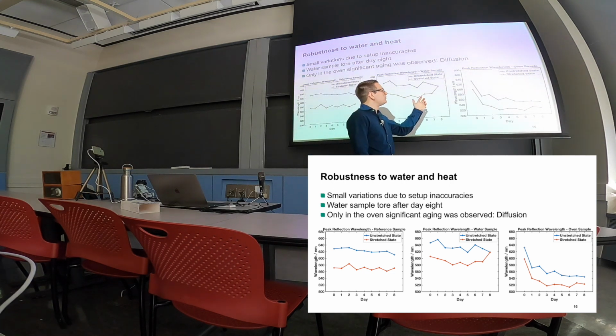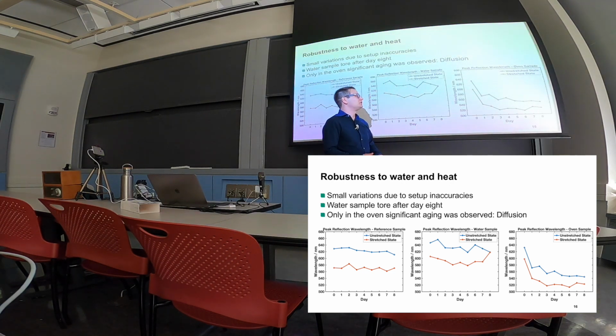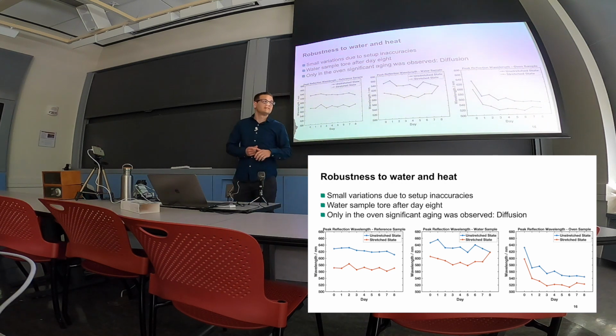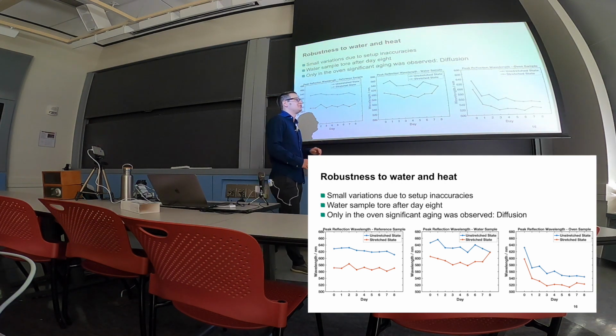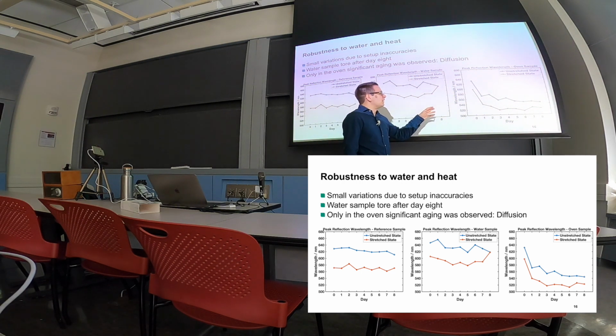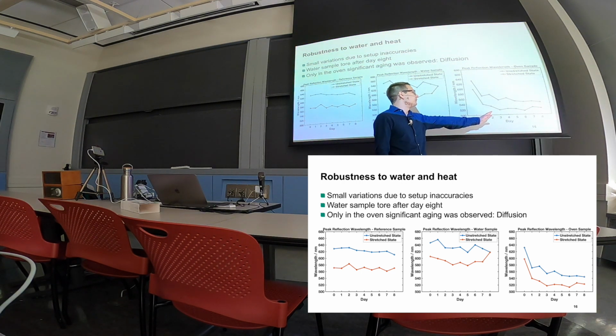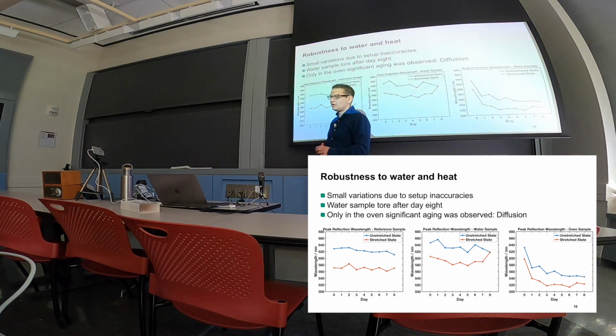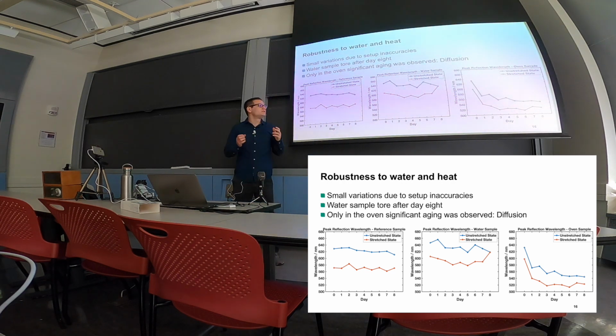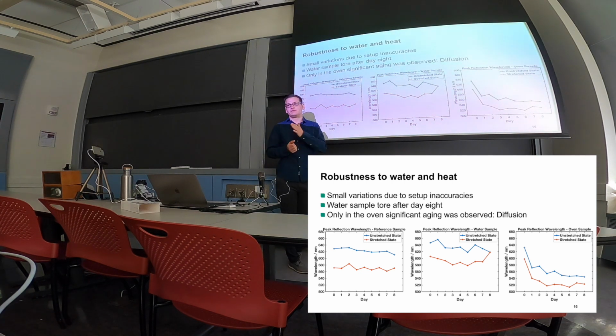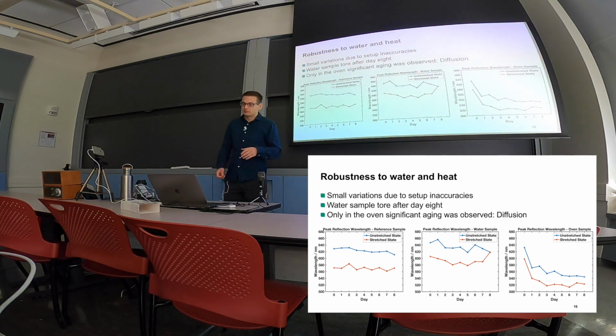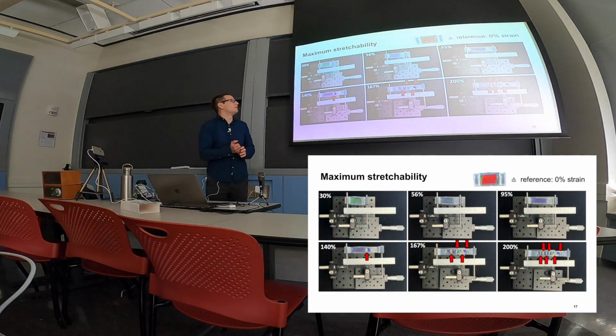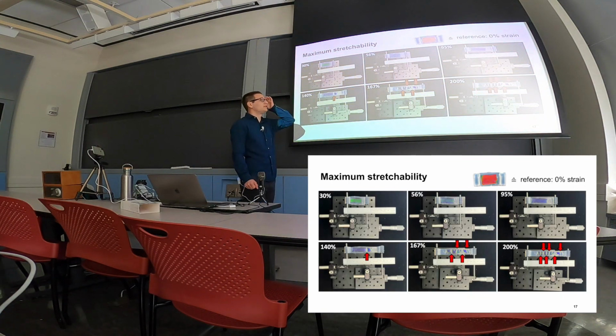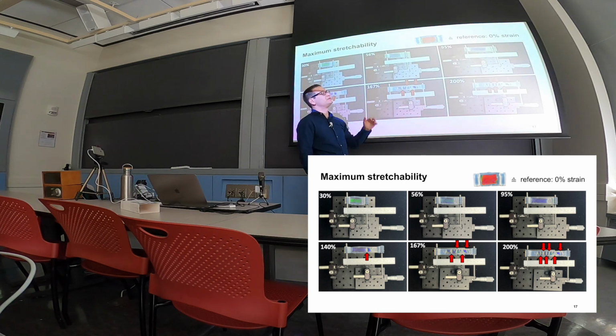And then for the last sample, we can see a significant aging in the first 3 days, which might underline that there is a diffusion process taking place, because diffusion is usually proportional to temperature, and so the diffusion coefficient as well as the diffusion length increases when increasing the heat. However, we can see that after 3 days, there's no aging taking place anymore, so it might be possible to just produce the color changing material in the infrared state and then pre-age it in the oven over a course of 3 days to let it shift into the red peak wavelengths, and then it should also be stable in this surrounding.